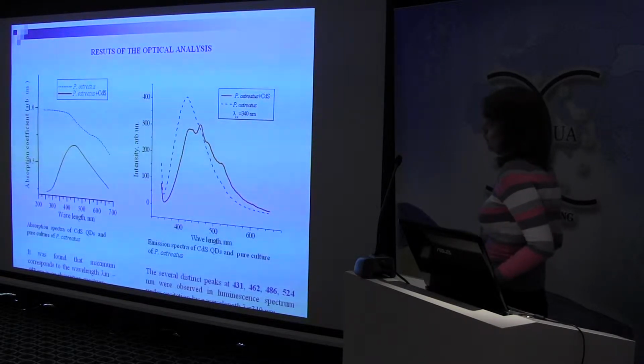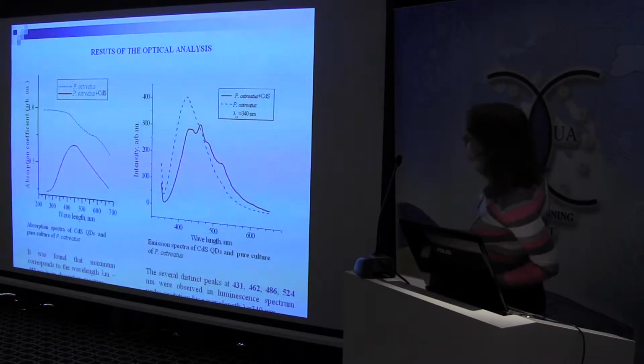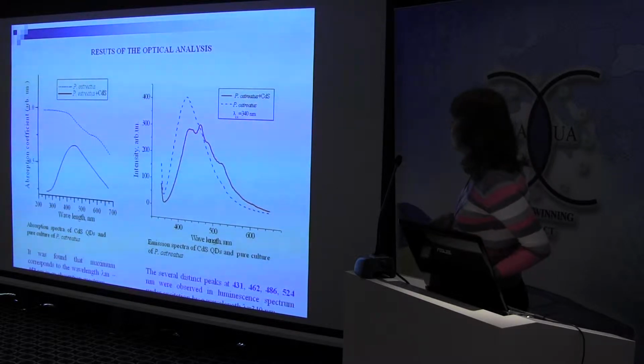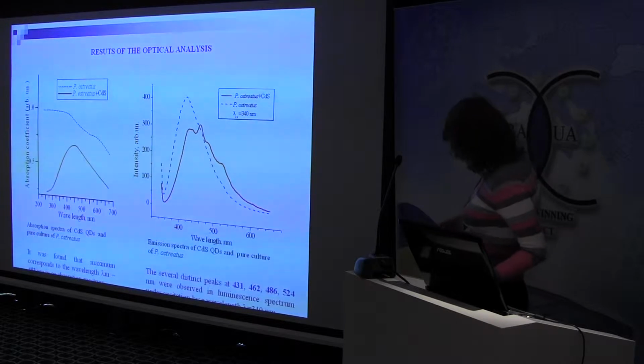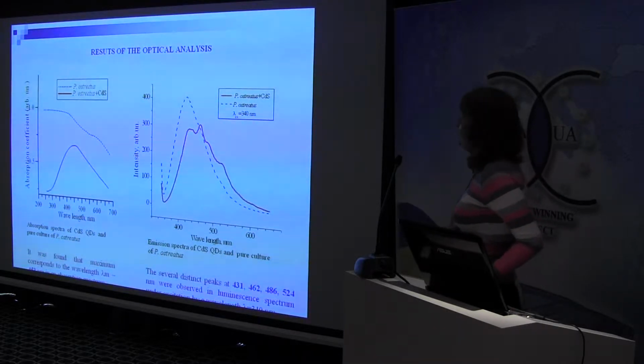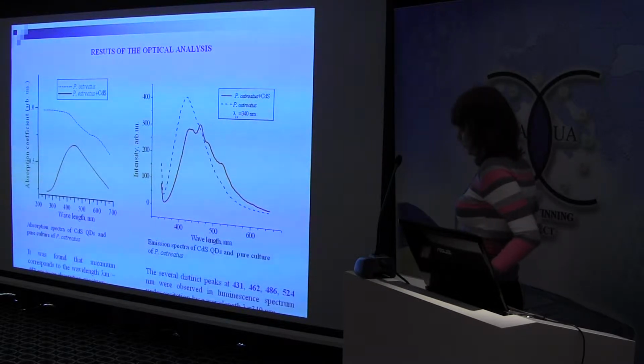So, our results. It was found that the maximum in the absorption spectrum corresponds to a wavelength of 453 nanometers.